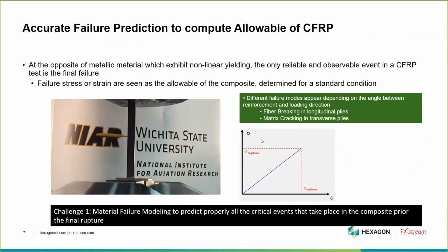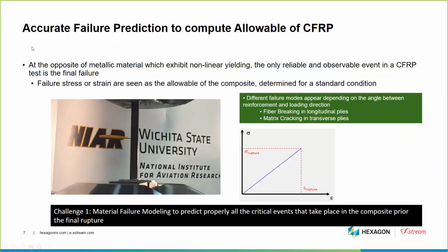So once we started to develop this platform, we had to tackle a series of challenges. And the first challenge is obviously to be able to make an accurate prediction of the failure of the coupon. And as opposed to a metallic material, which exhibits a very clear modification in its behavior, like non-linear yielding, for composite, the only reliable and observable event is the final failure. And most of the time, what is considered as the allowable is the final stress or the final strain.